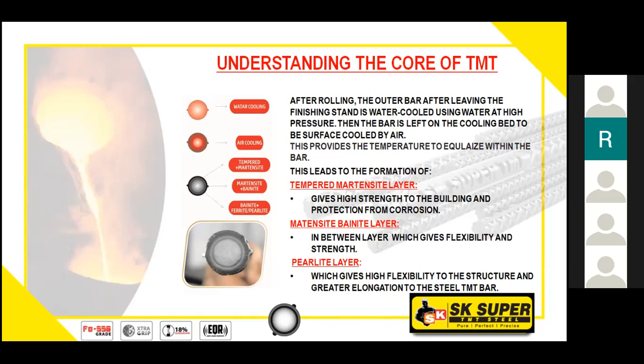If on one part of the bar the thickness of the hardness is more, and exactly on the cross opposite side the thickness layer is less, the bar will crack while bending or the bar may break. So the most important thing while manufacturing good quality steel is that the center of the 3 rings has to be at the same place. Now, coming down to the weight complaint, what I was talking about.